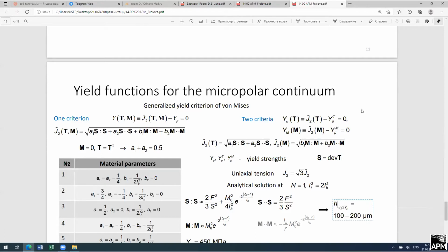So it was of interest to check if the micropolar solution, when we have big values of stresses in the vicinity of the border, can lead to such flow, and in this case it also should be accounted for in further models. And here we use the generalized yield criterion of von Mises for micropolar continuum, and usually one criterion is used for couple stresses and stresses, or two different criteria for different stresses.